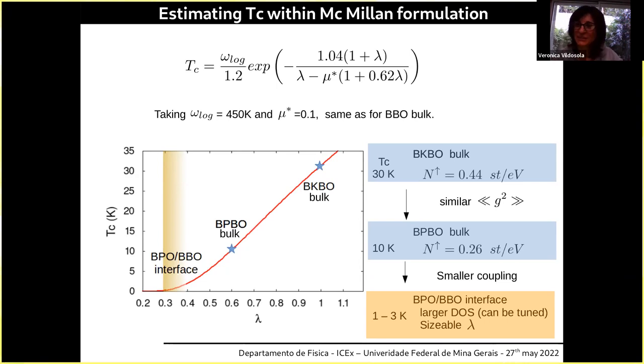I introduced the experimental crystal structure and relaxed around that point. I'm not predicting that the film wouldn't be monoclinic. Still, it worked, and that's impressive. I was wondering if you had considered these additional distortions as some free parameter. No, because I only study bulk in order to understand the bilayer, and in the bilayer the experiments say that it is monoclinic.